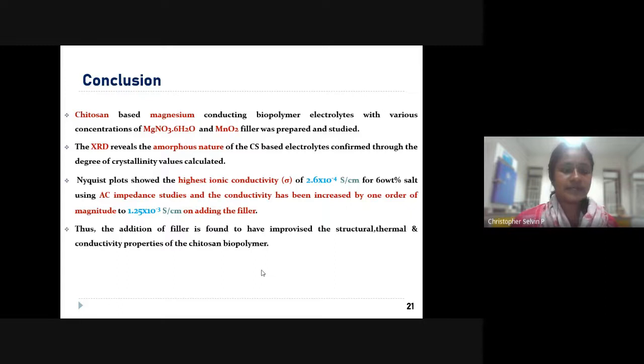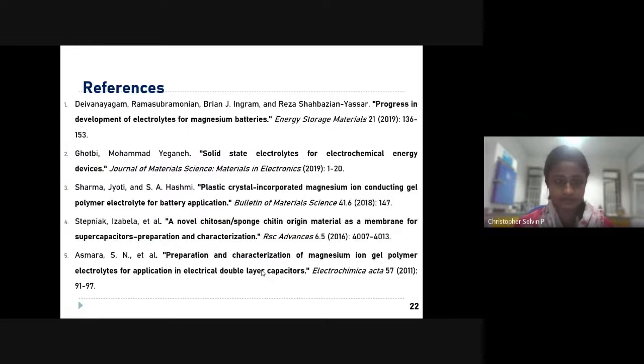So finally, we conclude that chitosan electrolytes with various concentrations of the magnesium salt and MnO2 filler have been prepared and studied. From the study, we confirm the amorphous nature of the electrolytes, which was confirmed using the degree of crystallinity values calculated. From the Nyquist plots, the highest ionic conductivity of 2.64 × 10^-4 Siemens per centimeter has been obtained for 60 wt% of the salt. The AC impedance study shows that the conductivity increased by one order of magnitude on incorporating the filler, to 1.25 × 10^-3 Siemens per centimeter. The addition of filler is found to have improved the structural, thermal, and conductivity properties of the chitosan biopolymer electrolyte. Thank you.